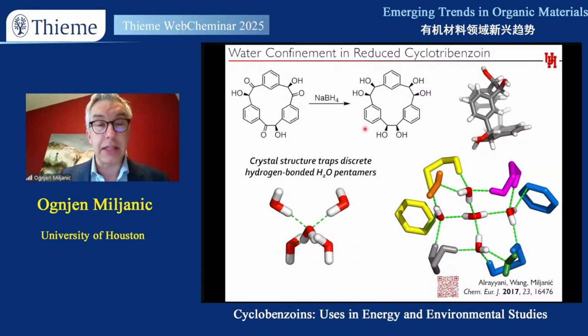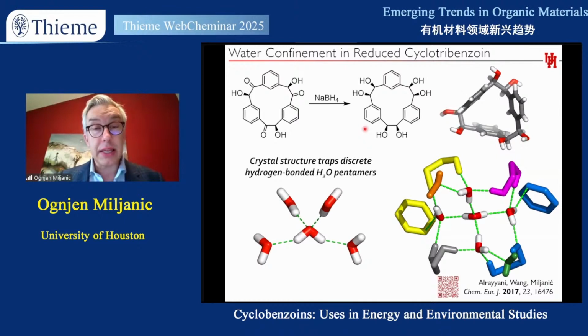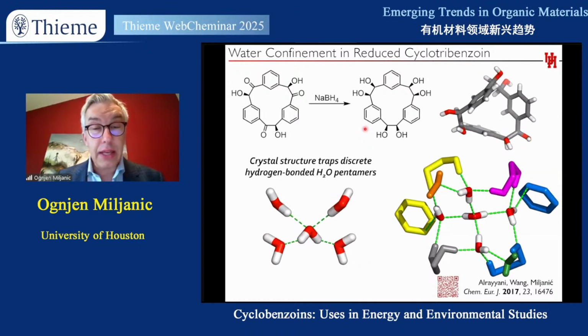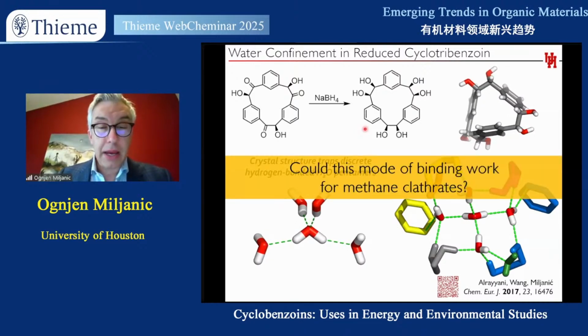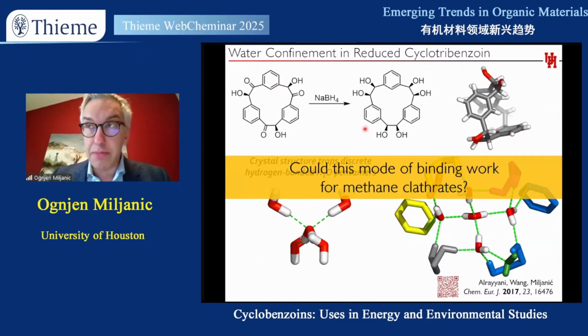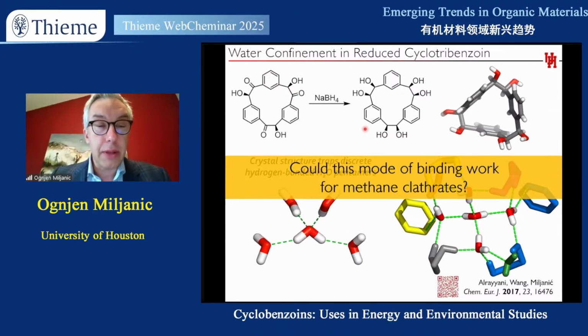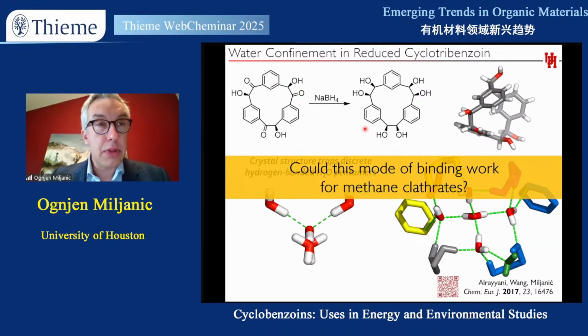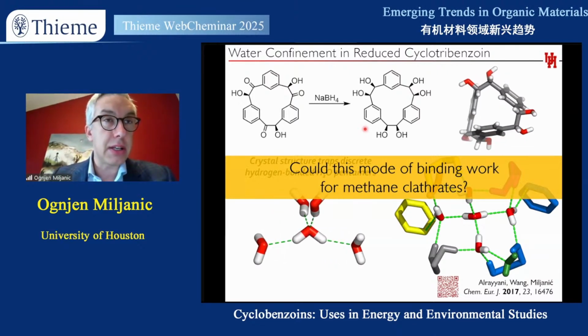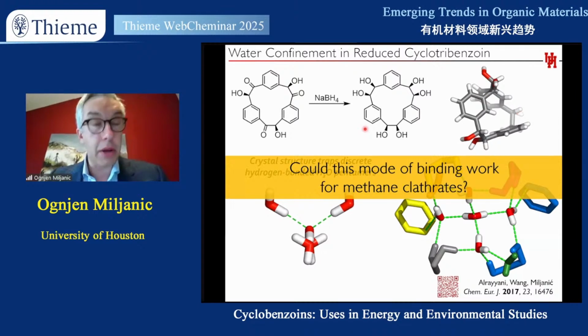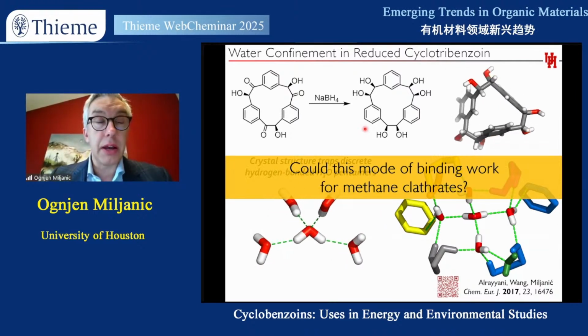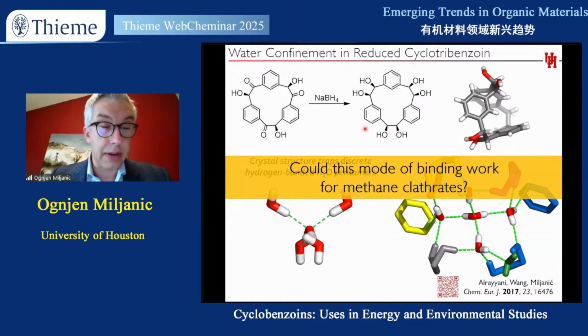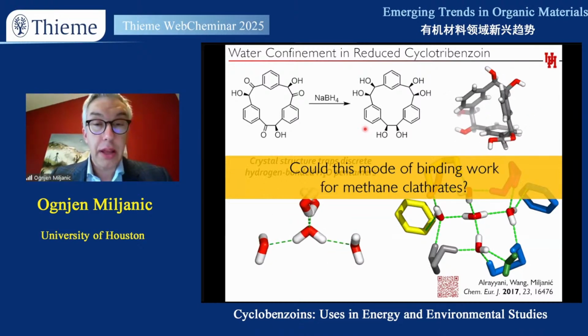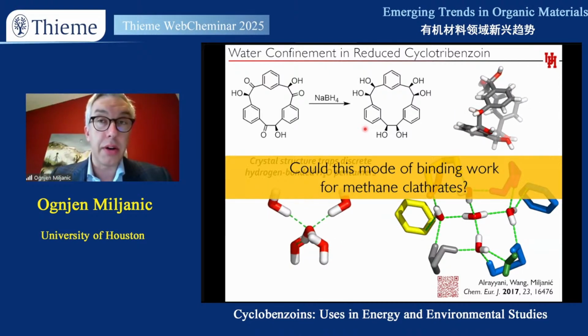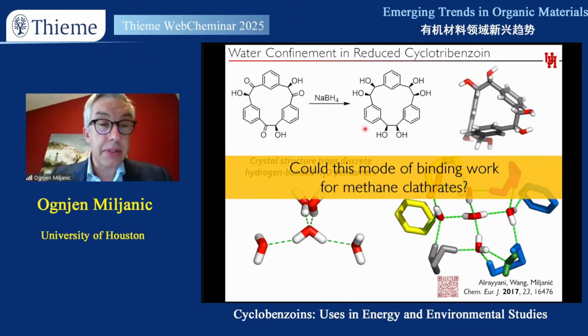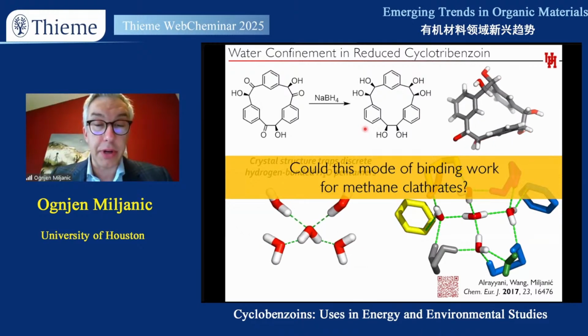It has hydrophobic parts and hydrophilic parts, but in the solid state, it creates a cavity which is very hydrophilic and binds these pentamer water molecules. And this has inspired us to start looking at other derivatives with many OH groups and to see whether we could expand this binding cavity so that we can bind larger water clusters, especially clusters including about 20 water molecules. Why would we want to do that? Well, because these are structures which are observed at very high pressures on the bottom of the ocean, where methane molecules are included in this crystal structure of water, which has pores inside. Unfortunately, these clathrates are not stable at atmospheric pressure, so they really fall apart.